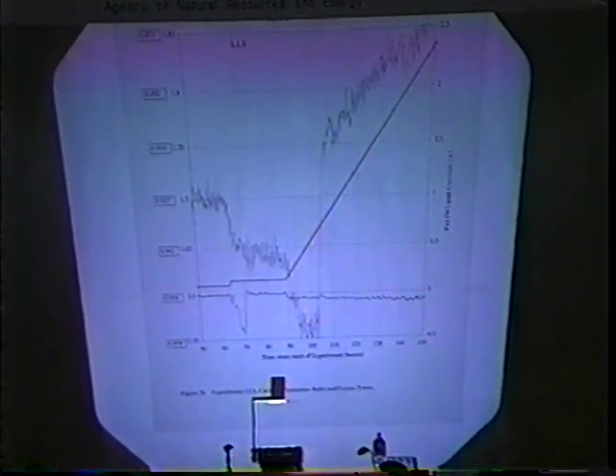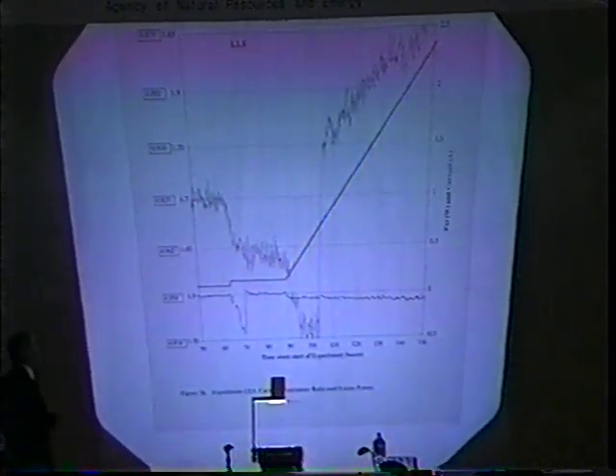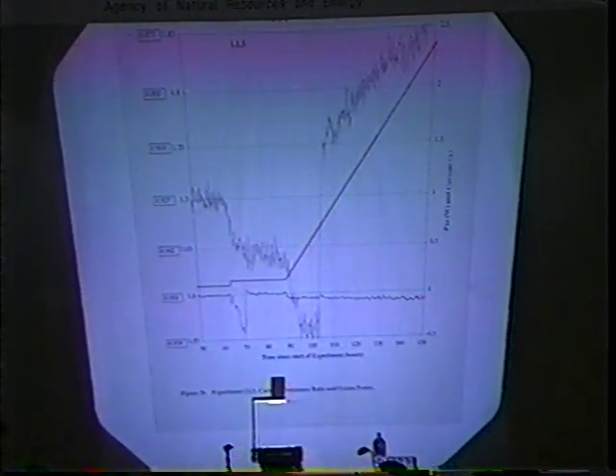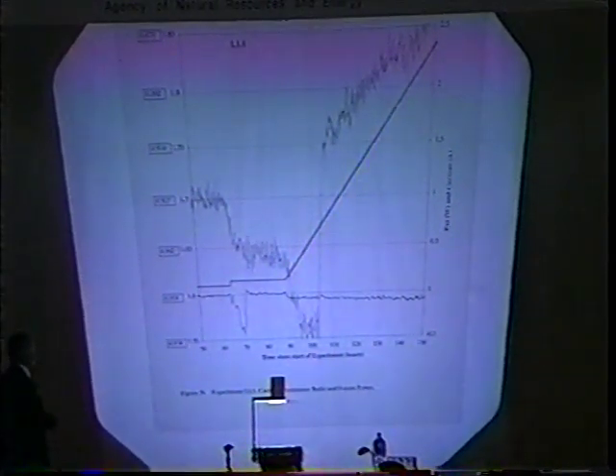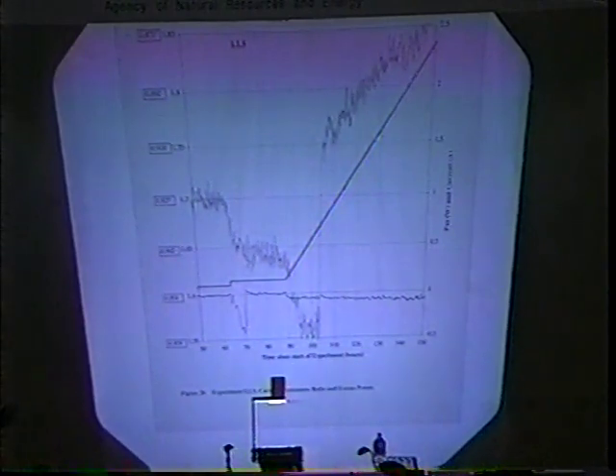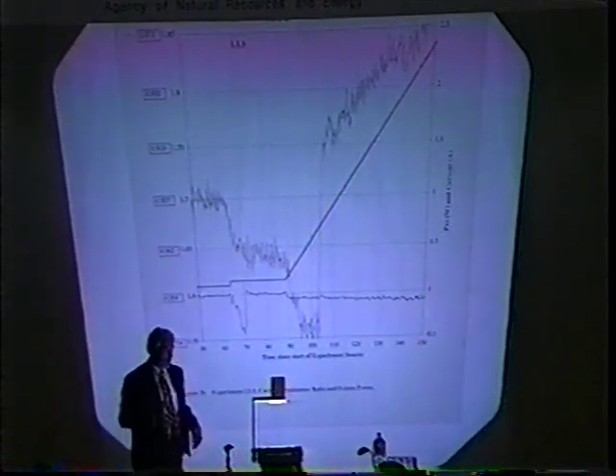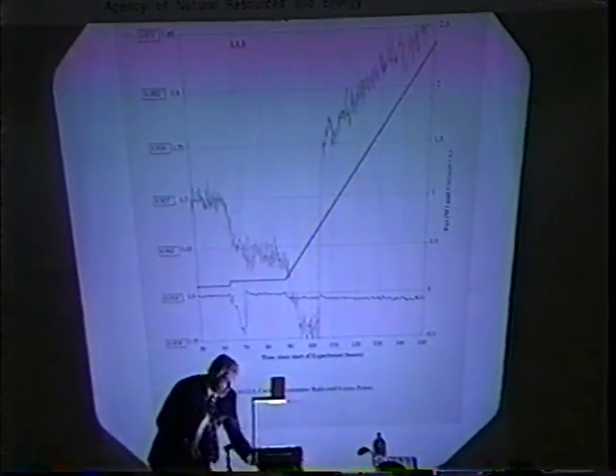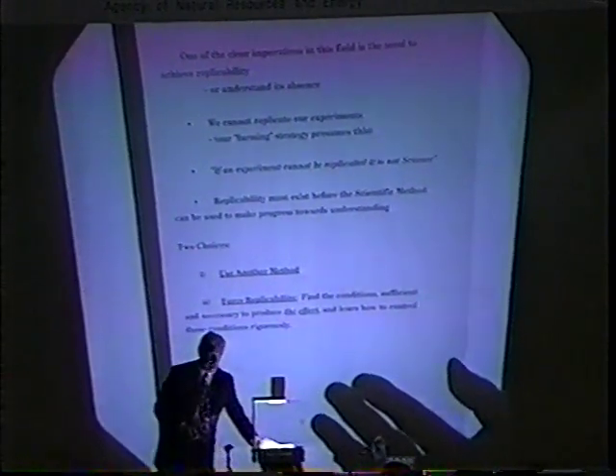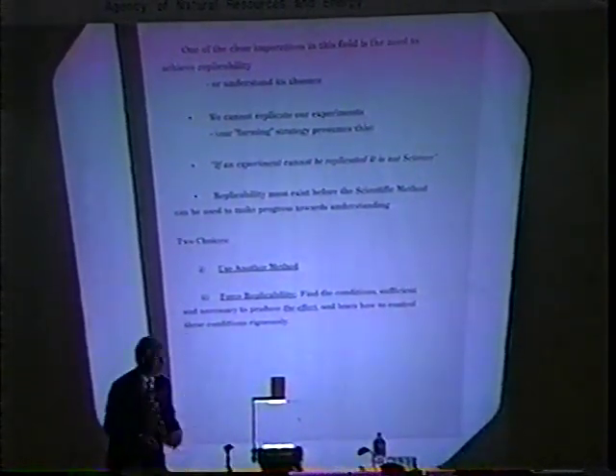The calorimeter goes into a small endothermic region due to the non-steady state response. As the power in the system is lifted up, the heat capacity is required to be satisfied. The calorimeter shows a very small endothermic response, and the cathode vastly deloads from 0.97 down to 0.91, and then rapidly deloads thereafter and was not able to be loaded satisfactorily again. And this is a problem. This is a clear difficulty, this inability to replicate our experiments, one experiment to another.